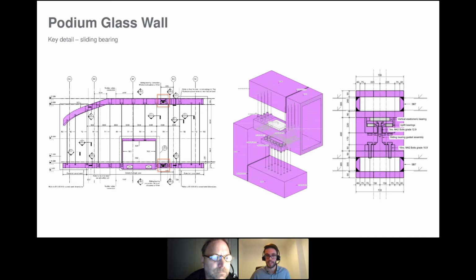bidirectional sliding bearing, which was kind of inspired by some sliding bearings that you can find possibly in footbridges, where the dead load is quite low compared to a few other loads, and therefore you can expect some uplift. Basically these two bits of beam are tapered and sit on top of each other and can slide thanks to neoprene and rubber pads. At the same time, you can ensure, especially at the bottom of the steel beam, that you can cope with the vertical downwards loads generated by the self weight of the structure, and the upwards vertical load that will be generated by the pre-stress applied to the rods.